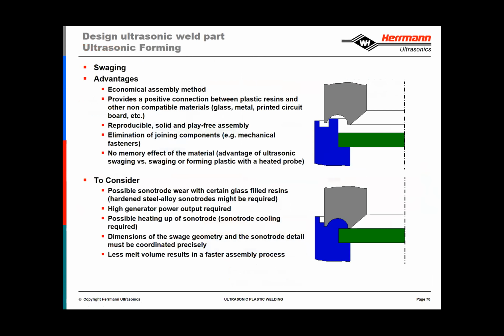So as I mentioned, in swaging, the wall is reformed. So here we have the before picture and the after picture. Calculating the volume of the plastic and comparing it to the volume of the sonotrode is very critical, making sure that after welding, the melt that was created doesn't flow outside of the containment area.